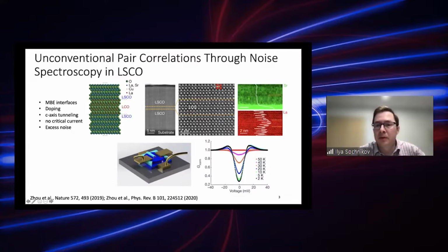These are MBE grown samples. They are as perfect as they can be. Interlayer diffusion was primarily ruled out by electron microscopy techniques, and we actually know that these layers don't carry critical current. The typical tunneling spectra are shown here. This is a normalized conductance, meaning the spectra were symmetrized and some background was removed. They show coherence peaks at the expected value for the gap, but there are always some states in the gap, and they never show critical current down to dilution refrigerator temperatures.